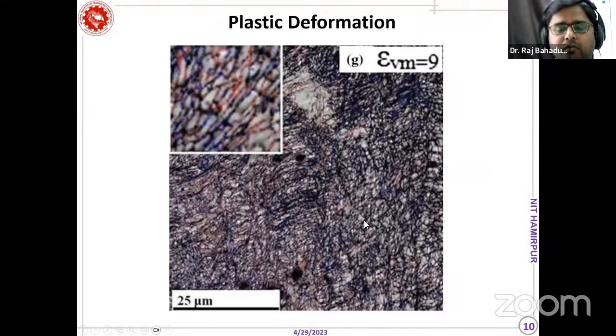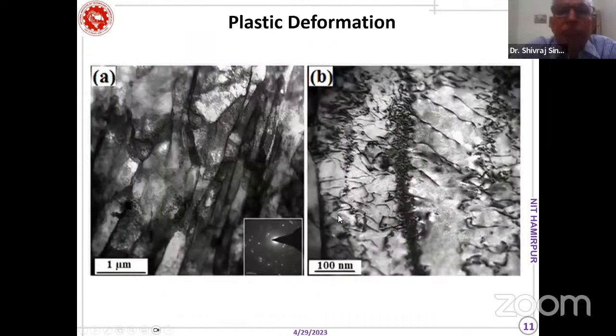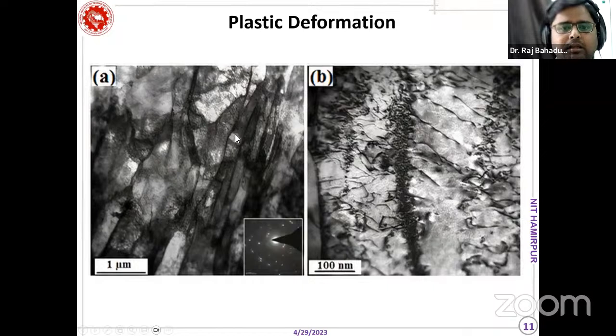Then you can see the microstructure is fine, in the range of ultrafine grain, and the typical grain size is 0.2 micron. So this is the result of severe plastic deformation, basically of ECAP deformation. And if you see the electron micrograph, basically the transmission electron micrograph, you can see the features which are very fine. The grain size is 0.2, 0.3 micron. And this is the dislocation structure we have captured at very high